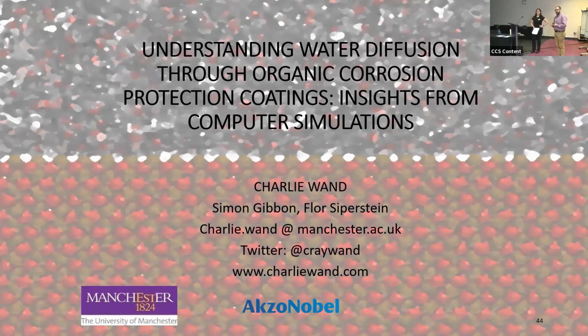Yeah, do you want to go front here first? That was a fascinating talk, thank you. I didn't quite understand how you decide what water is present initially, or do you put it in initially, or do you diffuse it in after the coating's been formed? Yeah, that's a very good question. I put it in initially because it's much easier than trying to get it in once the coating is formed. But I have validated this by making the coating that way and then taking all the water out and checking that the coating that remains is the same as it would have been without any water there. So we're essentially assuming that we've got an equilibrium system here.